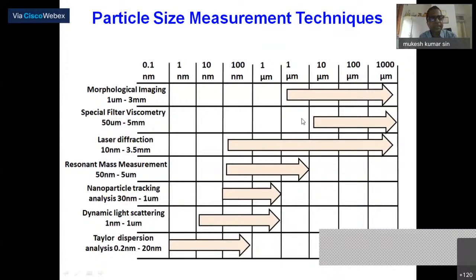Another technique, laser. This technique is capable of measuring particle sizes from 10 nanometer to 3.5 mm. Resonant mass measurement technique. This technique has the potential to measure particle size between 50 nanometer to 5 micron. Nanoparticle tracking analysis. This technique is capable of measuring particle size from 30 nanometer to 1 micron.